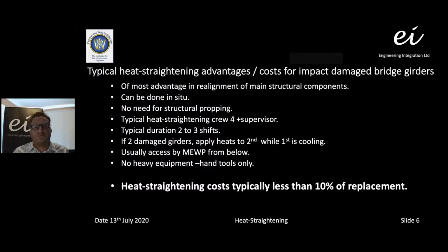There's a very low number of operatives required during a heat straightening process. We would generally take 4 crew to site with a supervisor. The typical duration of the project would be 2 to 3 shifts, depending on how many heat cycles would be required. When we're actually undertaking the works, if there are 2 damaged girders, we can alternate between the girders that we're heating. So we heat one, allow it to cool, and then we heat the next. So that makes us very efficient when we're actually working on site.